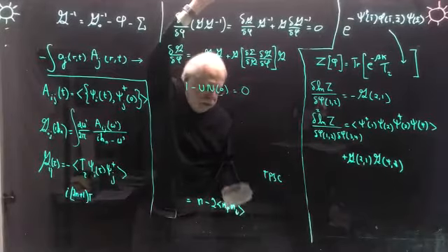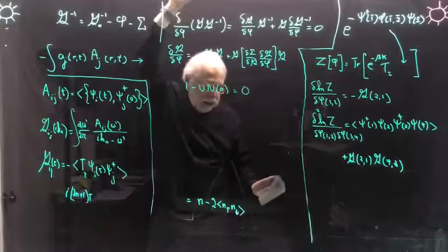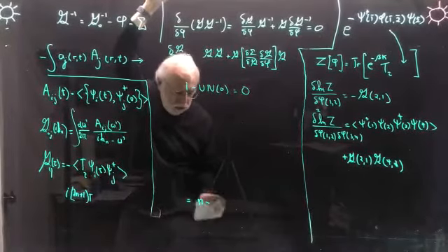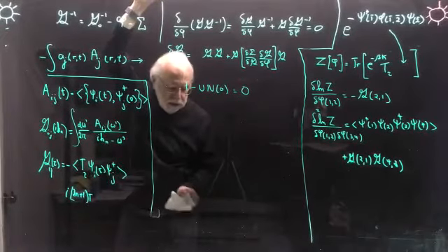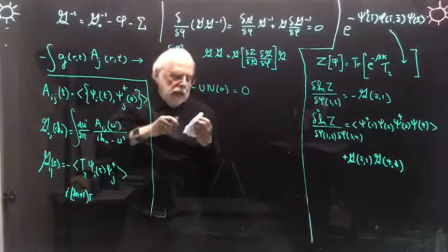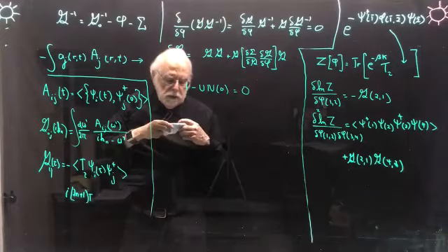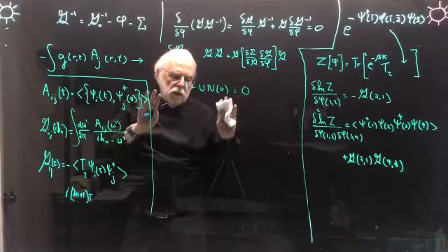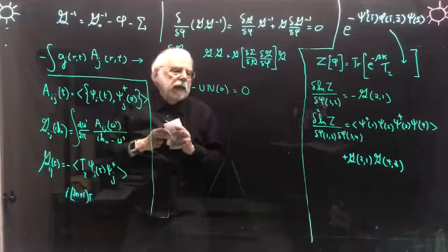So broken symmetry, you can see, comes from, you can put some small stray fields and then let them equal to 0 at the end of the calculation. So broken symmetry occurs in the infinite volume limit, where you cannot interchange the order of limits. And associated with that, there's rigidity. In other words, the spins will all be aligned. And there's also a Goldstone mode. So if the symmetry is continuous, you can restore it like this.